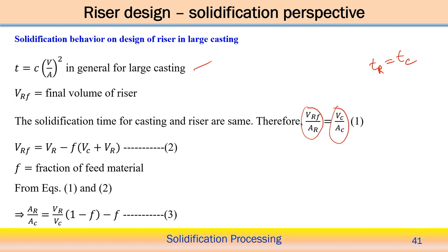So that is what we get from this expression, the general relation for the casting. Now this is equation 1. Now the final volume of the riser VRF indicates the final volume of the riser. So the initial volume of the riser VR plus F into (VC plus VR), because this second right hand side part indicates the total volume loss, or shrinkage volume, during the solidification. So F indicates the fraction of the feed material.